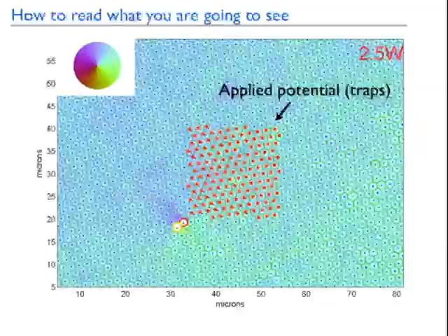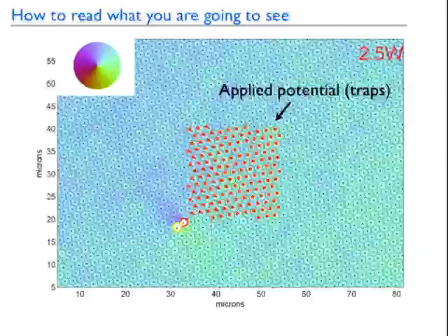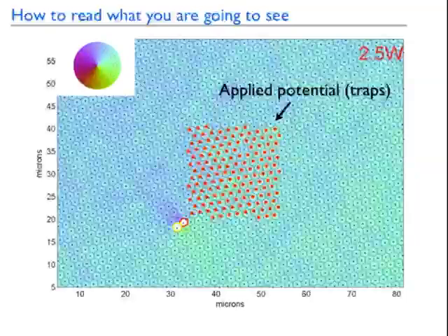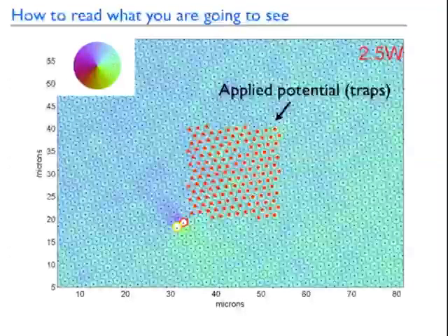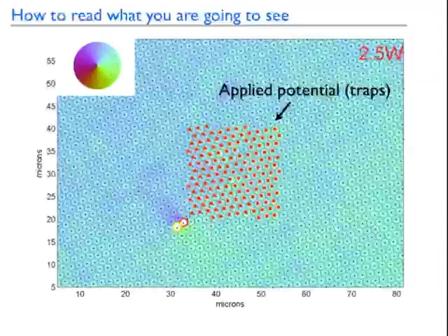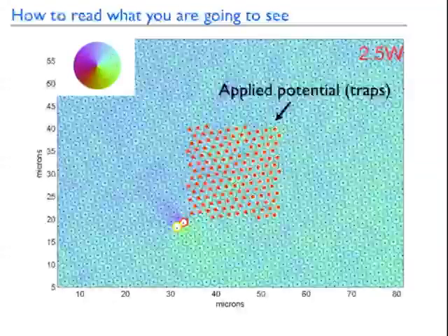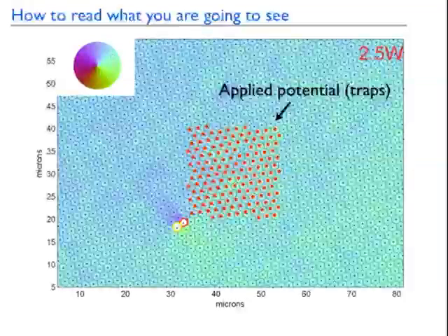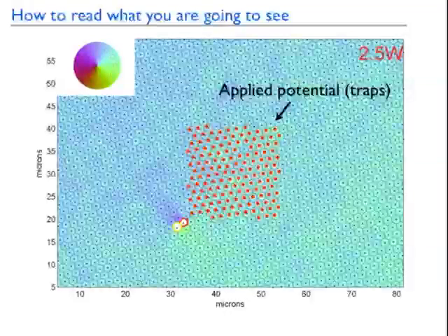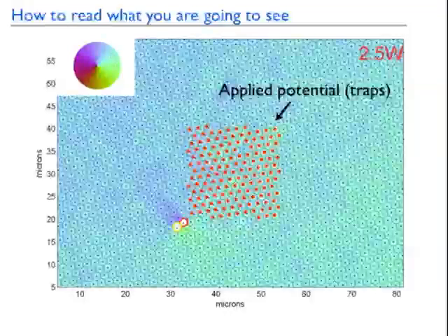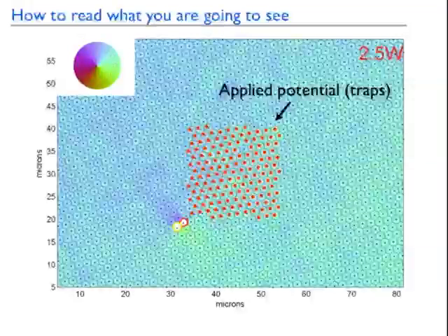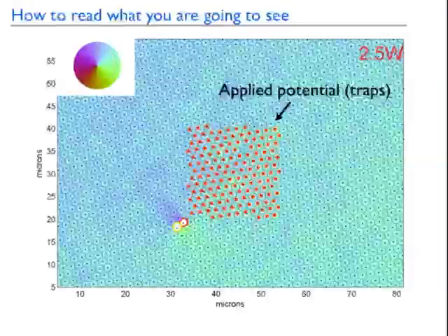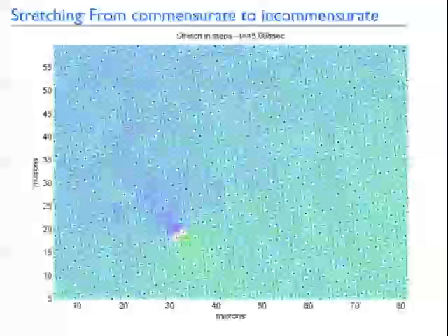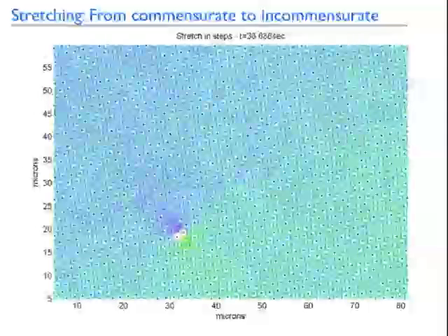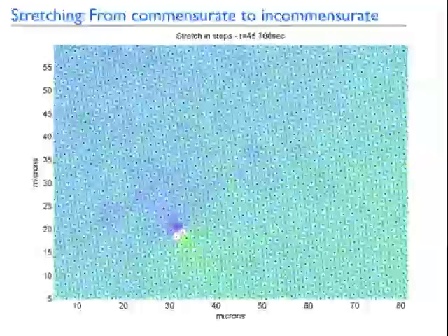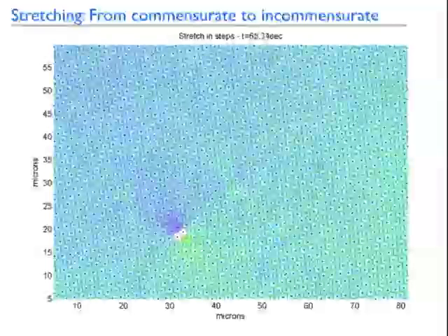But this is what I wanted to show. So what I'm going to do here is I have a single dislocation here, and the dislocation has these extra rows which are going out here. If I dilate the crystal in this region, the dislocation will want to move that way, right? Because it's got some extra density, so it wants to fill in where I've lowered the density. But this direction is climb, and it can't climb. So when I start expanding the crystal here, it's got to figure out what to do to relieve that.